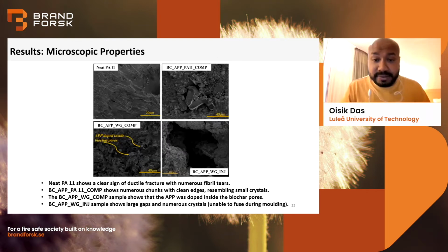And we also did scanning electron microscopy to see the manifestation of the APP doped biochar in the different samples. From the neat polyamide 11 microscopy, we see a clear ductile fracture. However, for the APP doped biochar in polyamide 11 made by compression molding, which is the second top figure, we see a lot of crystal-like structures are formed. And this was seen in the DSC analysis before, that this biochar particle has formed crystals, acting as nucleus sites.